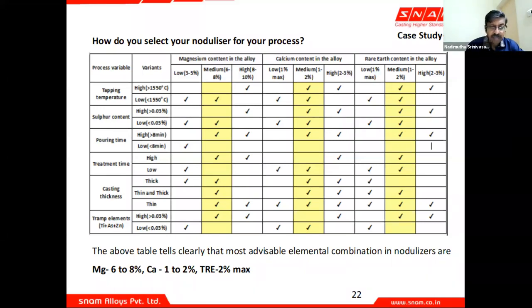My treatment time is high or low, depending on how I design my tundish, how I design my pouring time, and how I allow the treatment time. So if it is going to be high, then I want a higher magnesium content. The casting thickness is thick, so I want low, but if the casting is thin, I want somewhere medium, between 6 to 8%. So these are the combinations at which a foundry customer decides: this is what I want.